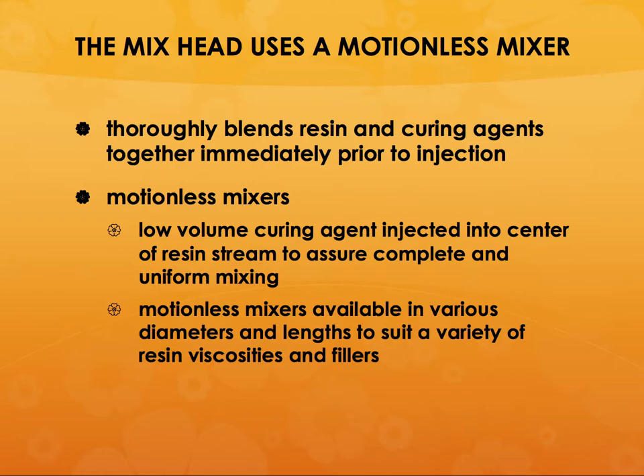Sometimes you also add fillers like chalk and fibers into this. You may also want to add fillers that will take up the reduction in volume, or the shrinkage in volume, as the resin is being cured. Suppose you have an epoxy resin, you may have about 10% volume shrinkage. So sometimes you may want to add some fillers to take up that shrinkage, so that you end up with a good final part with no voids at all.